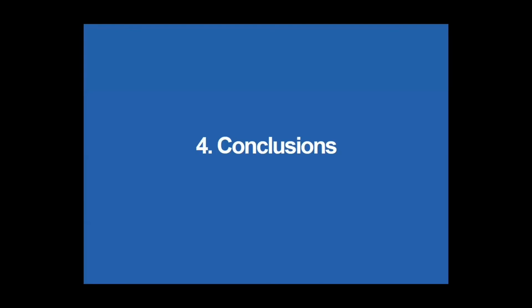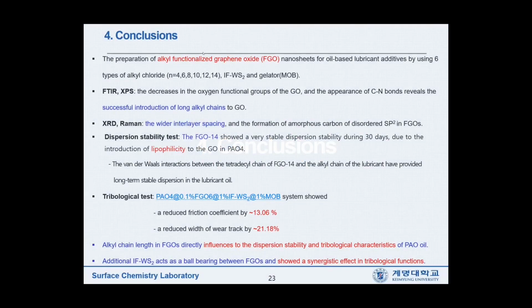Let me make a conclusion for the seminar. We have prepared alkyl-functionalized graphene oxide nanosheets for oil-based lubricant additives by using 6 types of alkyl chlorides. FTIR and XPS spectra show a decrease in the oxygen functional groups of the GO, and the appearance of C-N bonds reveals the successful introduction of long alkyl chains to GO. XRD and Raman spectra show the wider interlayer spacing and the formation of amorphous carbon of disordered sp2 in FGOs.